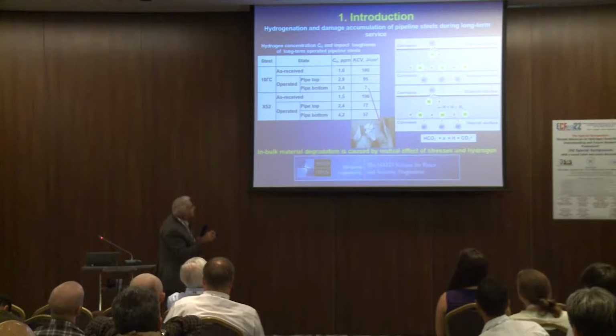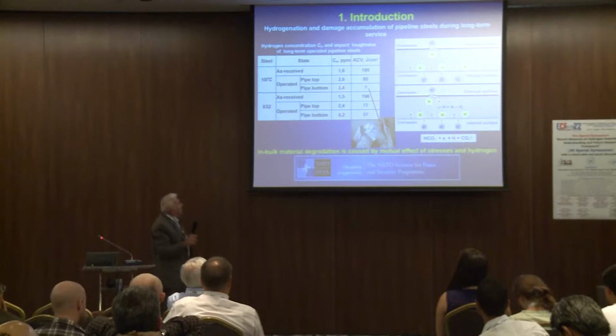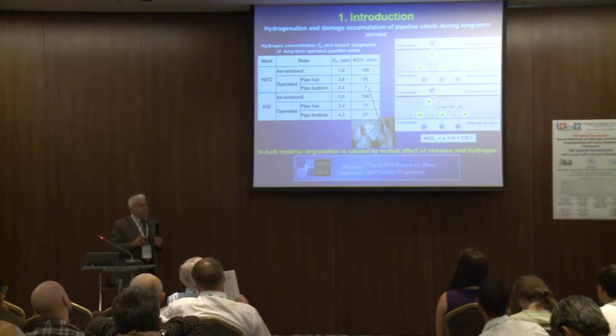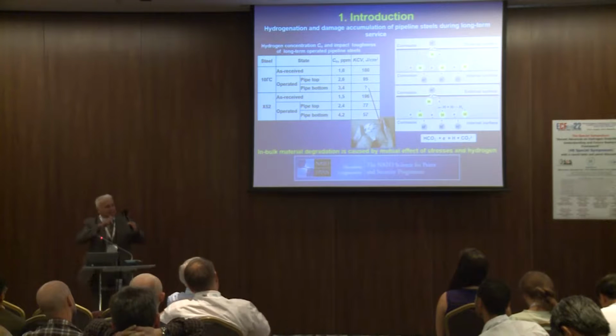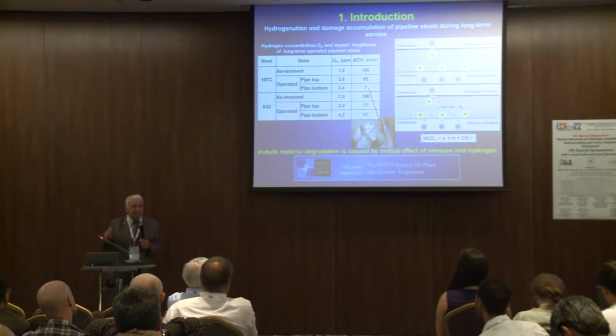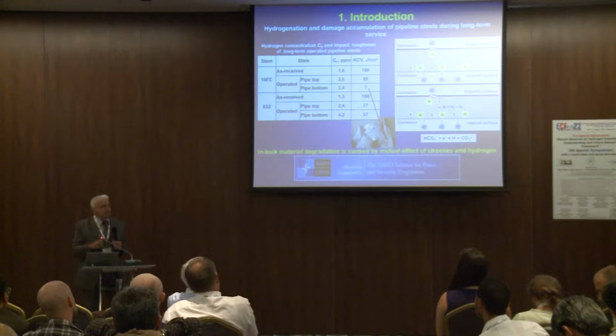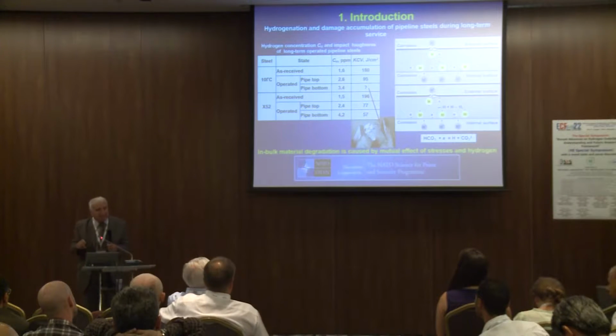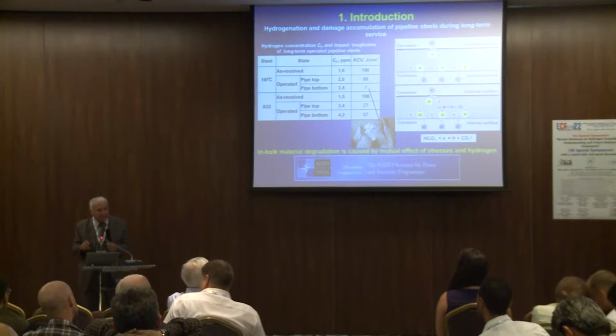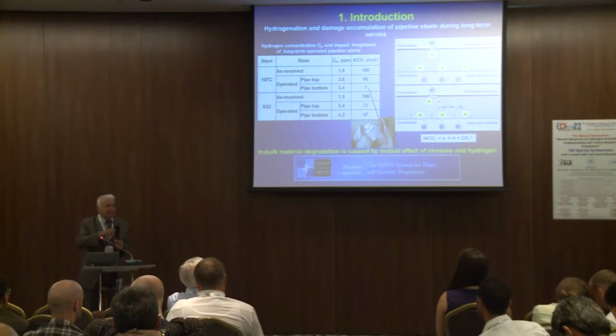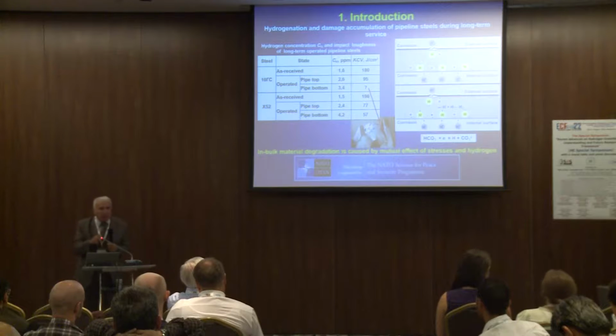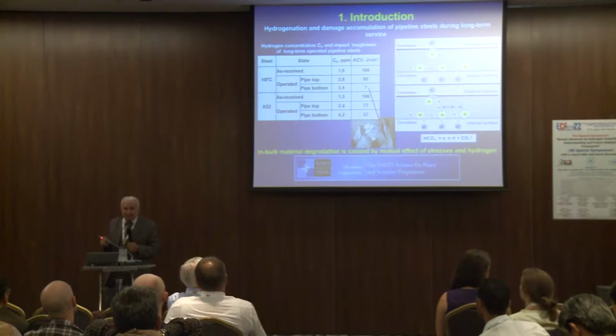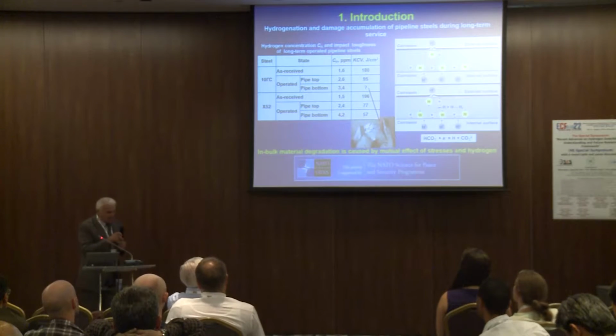And it is caused by the simultaneous effect of hydrogen and stresses, which promotes formation of damage on nano and micro scales, and finally the degradation of mechanical properties, first of all brittle fracture resistance characteristics.